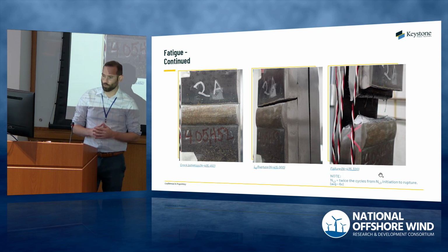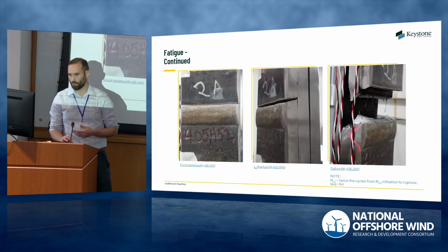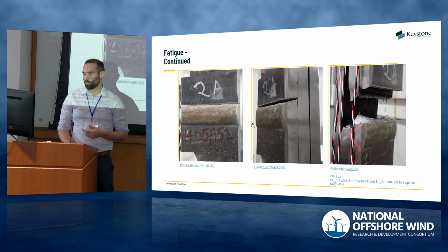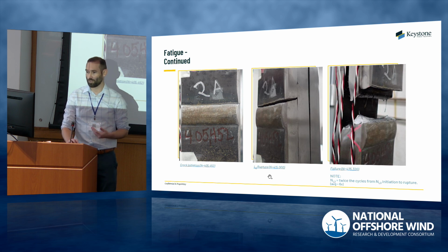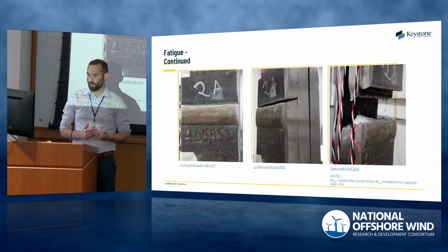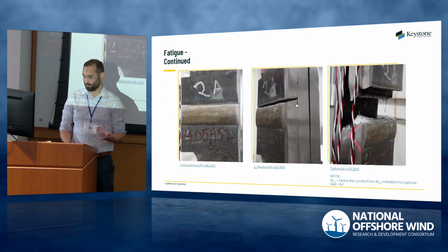One of the interesting things, we were theorizing that this would happen, but our test results actually do confirm it. We're seeing a natural crack arrestor in the multi-layer system. What you would expect from a monolithic test is if 1/3 of the cross-section was already consumed with a fatigue crack, that you would see a very short number of cycles to full rupture.